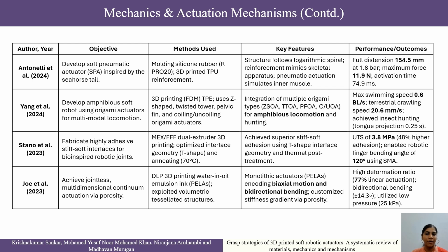Antonelli et al.'s seahorse-inspired tail actuator follows a logarithmic spiral structure with pneumatic actuation. It was able to achieve 154.5 mm full distension at 1.8 bar with 11.9 Newton force and 74.9 millisecond activation time, which is an impressive speed for pneumatic systems.